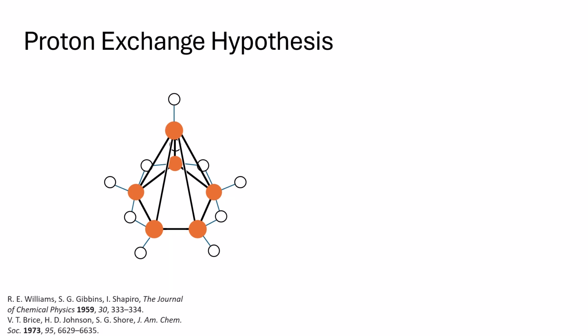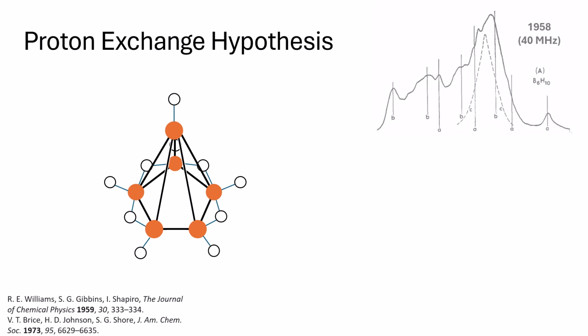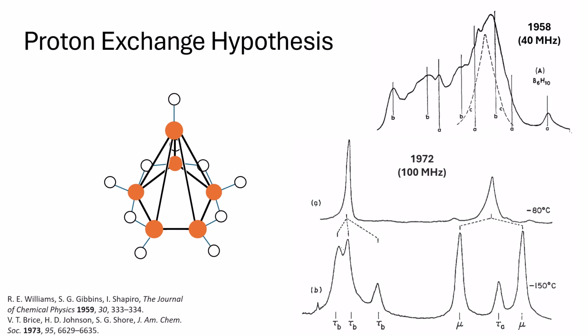A logical method to explore this proton exchange hypothesis is with proton NMR. However, the initial spectrum collected on a 40 MHz instrument was quite poorly resolved. This resolution was improved using a 100 MHz instrument in which at -80 degrees Celsius we only see 2 peaks, but more peaks appeared when we use -150 degrees Celsius for measurement. So these different peaks are assigned to different hydrogen atoms on our compound.